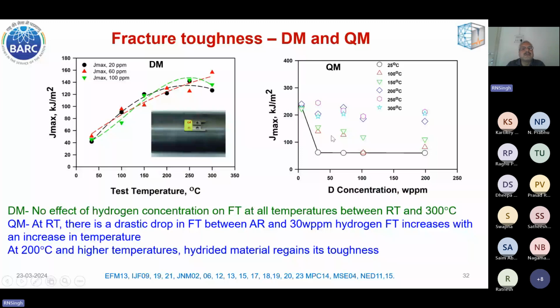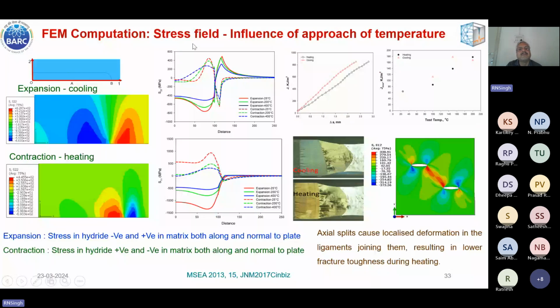Now, this is another illustration where we did some FEM calculation of the stress field in the hydride and the matrix surrounding it. What we saw depends on the tendency of hydride to grow or shrink. During heating, the hydride will shrink, it will contract, whereas during cooling, hydride will expand, it will precipitate out. So during cooling, you can see a boundary here. This is my hydride, which has transformed from initially zirconium into hydride, and it is surrounded by matrix. So we did this calculation.